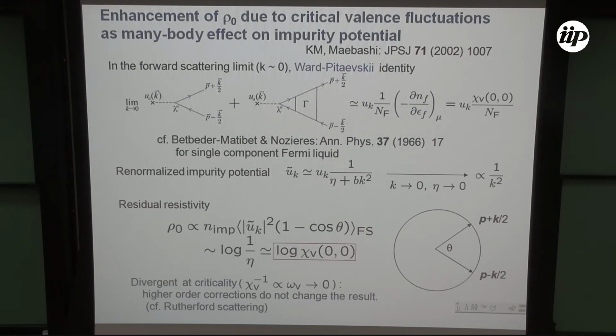This kind of intuitive picture is also derived by the so-called Ward-Pitaevskii identity, at least for the forward scattering, which means the renormalization by the many-body effect is proportional to the valence susceptibility, del nf over del epsilon f. Then by taking phenomenologically the k dependence like this, at the critical point, this gives a Coulomb scattering. Then the residual resistivity is proportional to a logarithm times the valence susceptibility, which diverges at the critical point.